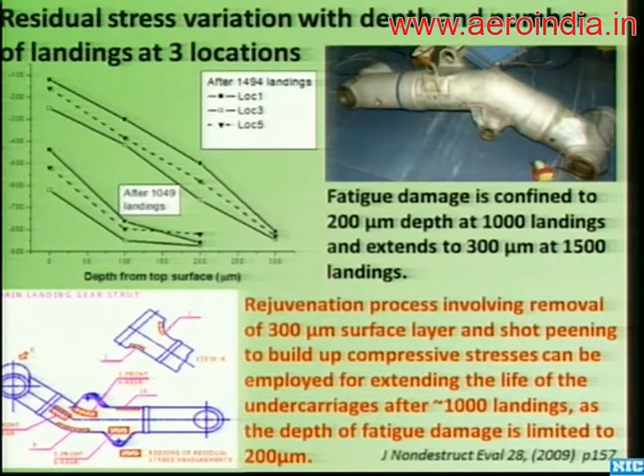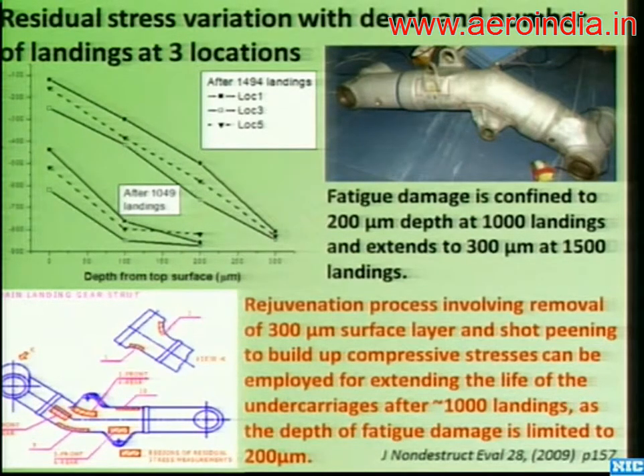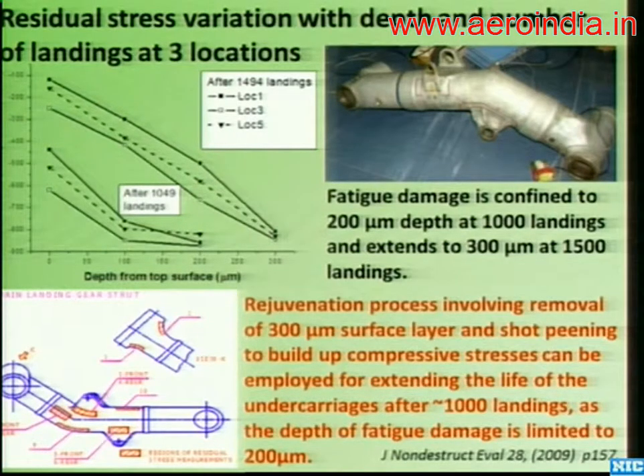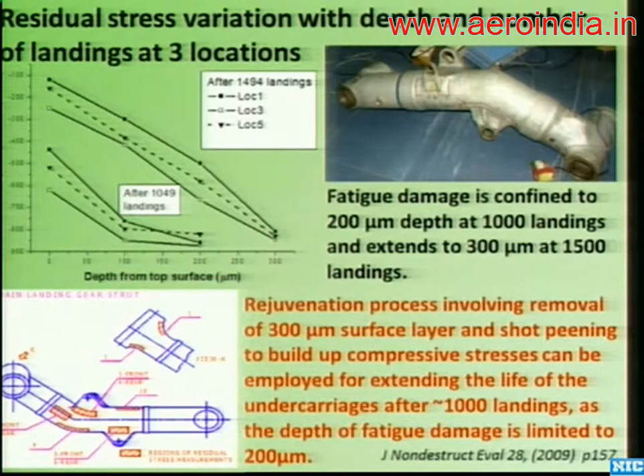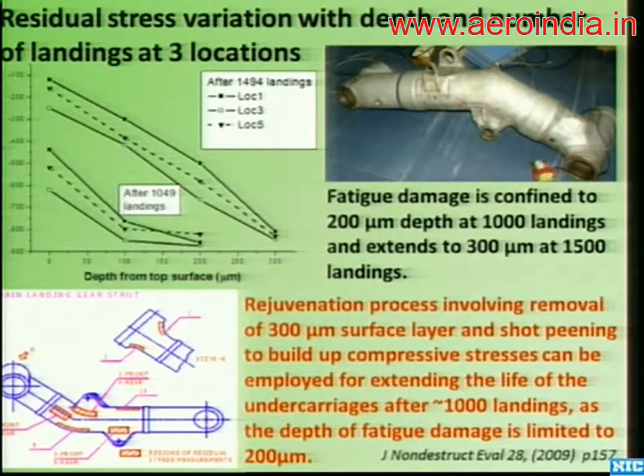We measured residual stresses after 1,000 landings and 1,500 landings to see how fatigue damage is progressing and when to renovate or replace. In India, some landing areas involve short runways or forced landings, meaning damage accumulation can be faster. We should know a priori the implications of a forced landing on residual stress redistribution, and may need to reduce the permissible number of landings for aircraft operating from short-runway air force stations.